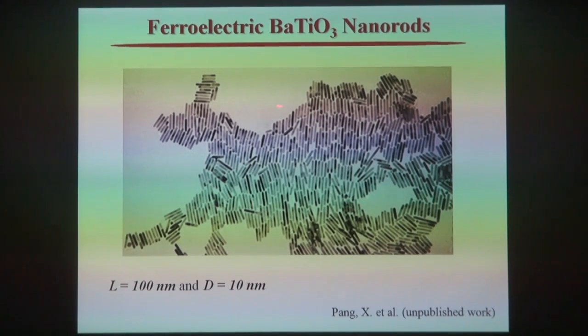Why? Because for ferroelectric materials, they have size-dependent ferroelectricity. Below a certain size you change the system from ferroelectric to paraelectric. So they change from tetragonal phase to cubic phase. That is for barium titanate nanoparticles. However, if you are able to make nanorods, you can investigate the aspect ratio effect. You can investigate the length effect on the ferroelectricity. That allows you to do some fundamental research.